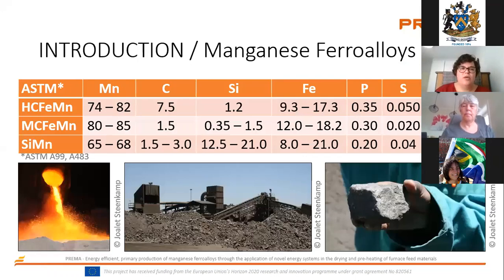So, manganese ferroalloys: there are basically three grades produced, all in South Africa. You get high carbon ferromanganese and silicomanganese, and they are primary alloys, produced from ores. What you'll notice here is that the high carbon ferromanganese has a high carbon content, 7.5%. Silicomanganese has a much lower carbon content, but a much higher silicon content, 12.5 to 21%. And then medium carbon ferromanganese is produced from high carbon ferromanganese, where the carbon content of the alloy is reduced.